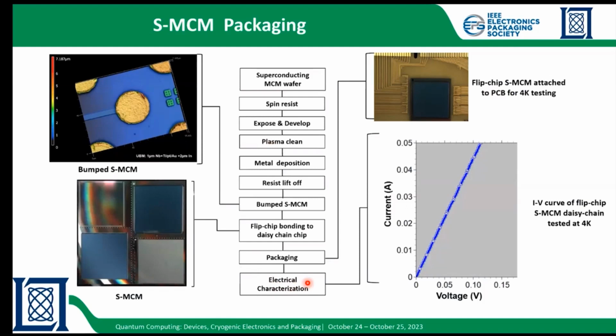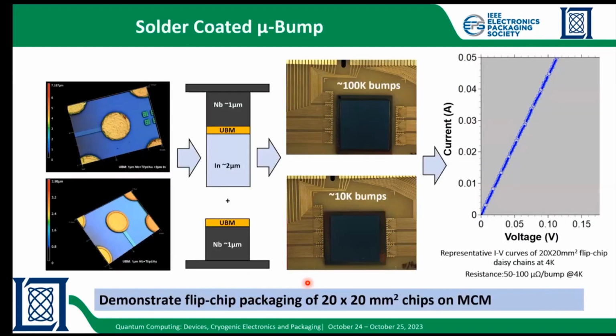So the micro bump design is going to be very, very critical. Here we have designed and fabricated a bump stack up with a 1 micron niobium pillar, niobium UBM, and then indium on top of that. This kind of micro bump configuration will be very critical for bump bonding a very large chip, like over here, a 20 millimeter by 20 millimeter chip.